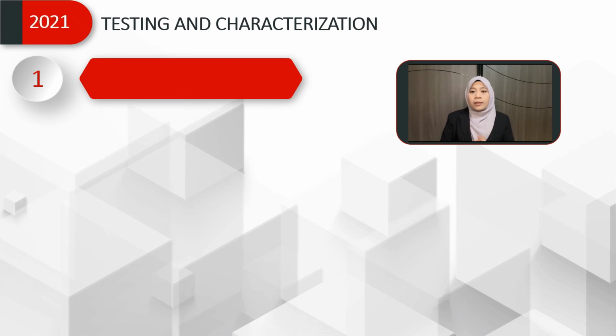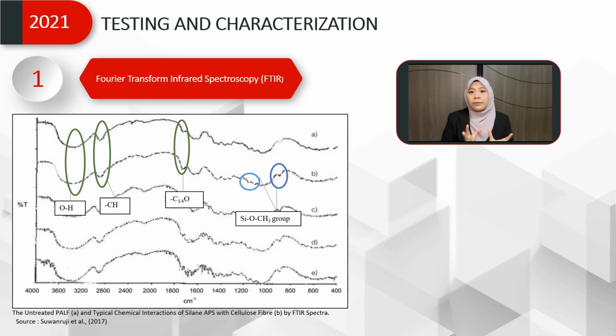For testing and characterization, first is FTIR. This figure shows that FTIR distinguishes silane-treated fiber from untreated fibers. A is the untreated PALF and B is the chemical interaction of silane with PALF. Between these two, the untreated PALF showed that the OH vibration from the cellulose peaks was broad, while the OH stretching peak was marginally decreased for the treated PALF by the chemical reaction of the cellulose